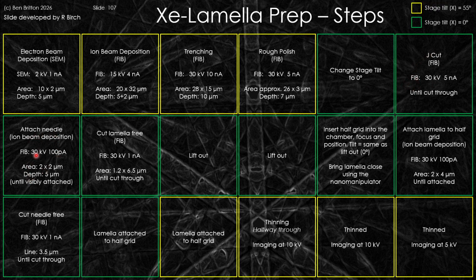We're then going to attach the manipulator needle. We're going to cut the lamella free. We're going to lift out the object. We're going to insert the half grid. So in our particular system, we have to break vacuum, put this sample in, and then effectively do the lift out. You don't have to in all systems. And then we can attach the lamella to the half grid. And then we can cut the needle free, so the sample is now attached to the half grid, and then we can do the thinning and full thinning of this. So that's the steps with conditions that we used for this steel sample.